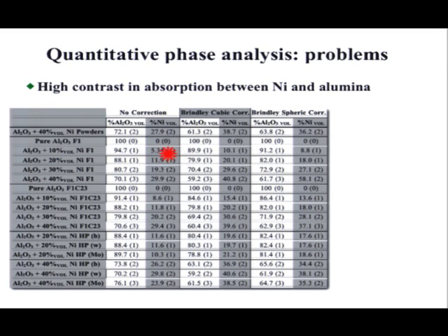And so you see, you put 10% of nickel and you get 5%. And nearly, 20 is 12, 30 is 20, okay? So then you apply the cubic correction. So suppose your particles are cube-like, okay? And you get a nice correction.